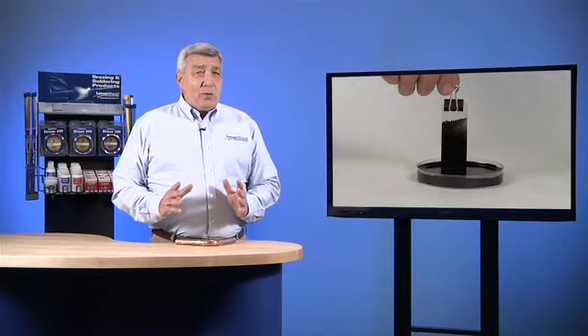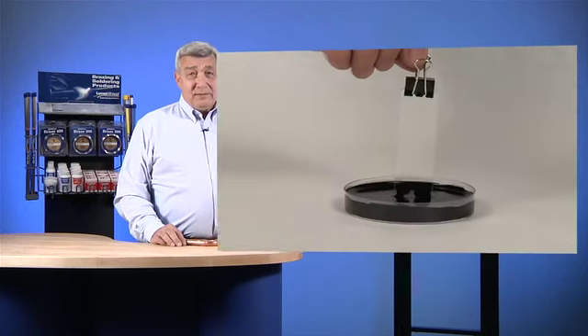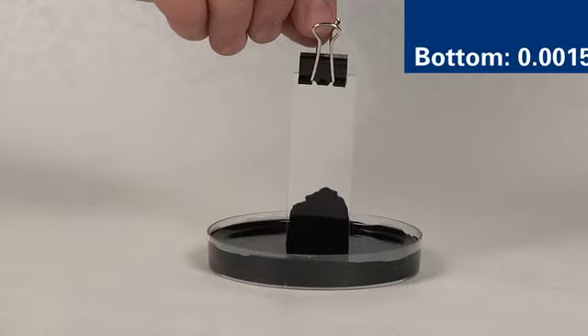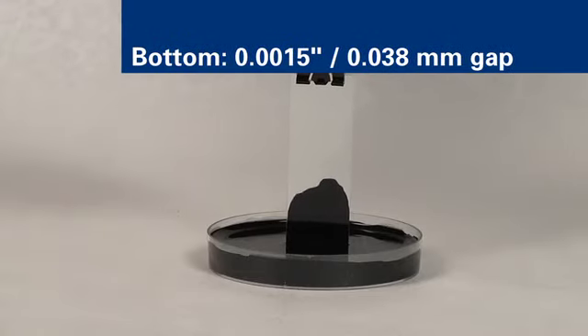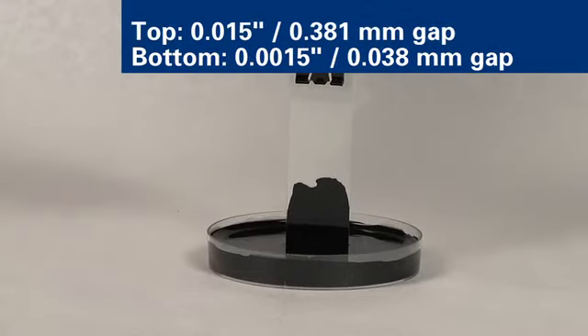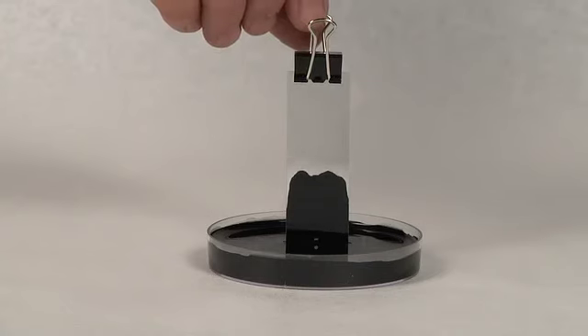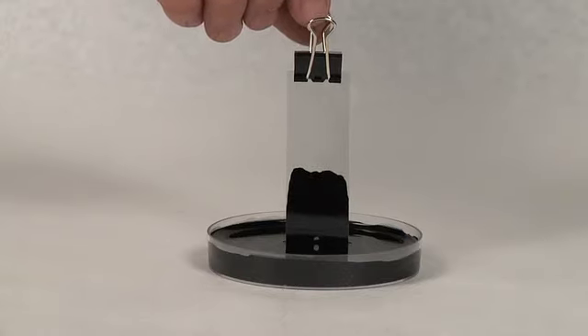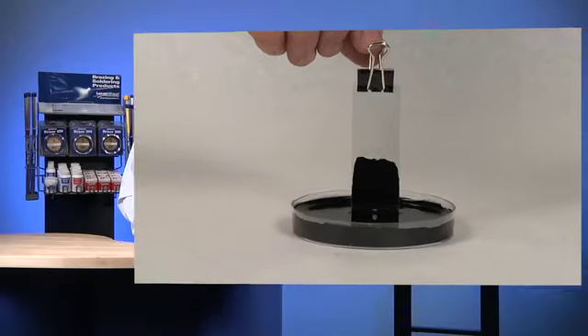Next, we'll demonstrate what will happen when we don't have a proper uniform clearance. These plates are separated by a 1 1/2 thousandths of an inch shim at the bottom and a thicker shim of 15 thousandths at the top. Now, when we insert the plates into the tray, we see the liquid can only rise part way. Capillary action will draw the liquid only to the point where the clearance is 5 to 6 thousandths of an inch. Then the gap becomes too large and capillarity cannot take place.